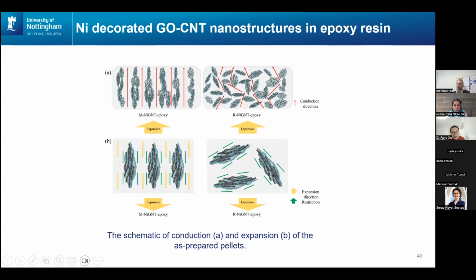We tried to understand why the CTE was reduced after applying the magnetic field. Looking at the right sample, the randomly distributed GNT and epoxy resin, when temperature increases it can freely expand. But looking at the left sample, the expansion is constrained because of the aligned nanostructure. I hope that makes sense.